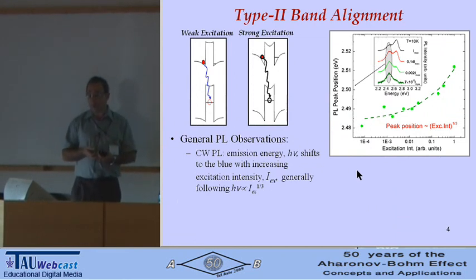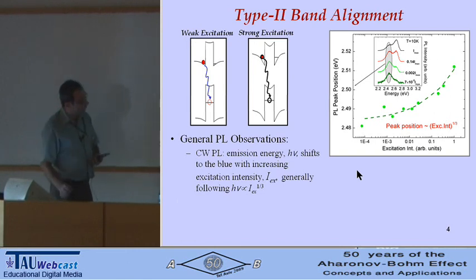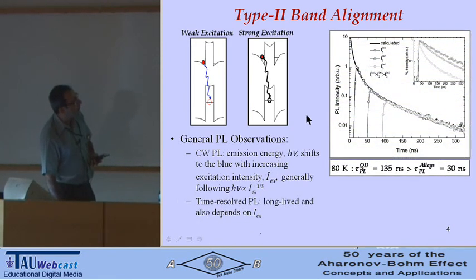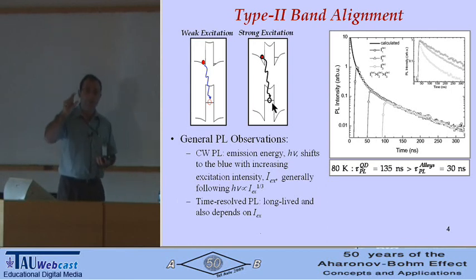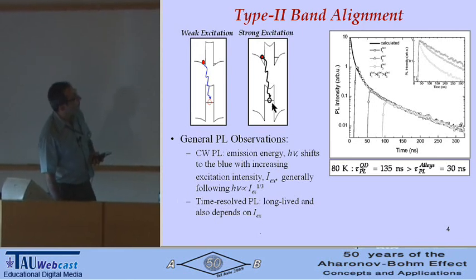So what is the general optical behavior of type 2 quantum dots? Again, for those who didn't work with that, you can show, and I'm not going to go into details, that if you have emission from type 2 band alignment, as I show here, weak excitation and strong excitation, you have a change of the band structure in such a way that CW emission actually shifts to higher energies with excitation intensity, and usually it follows the cubic root of excitation intensity. Then it has a certain behavior in lifetime: it's relatively long, because again the overlap of the wave functions of electron and hole is small because they're spatially separated. I'd like to point out that this is indirect in real space, but still a direct exciton in k space, so you don't need any phonon-assisted recombination for photoluminescence to be observed.